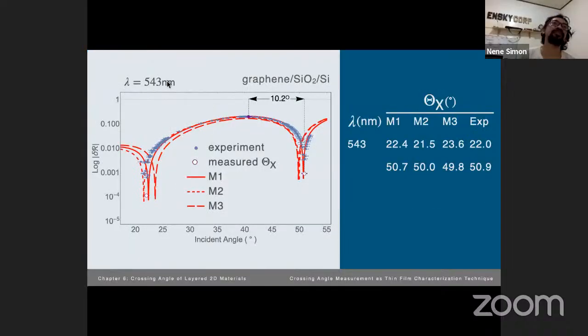So here is the degree of polarization for a 543 nanometer incident light. And as you can see here, model 1 predicts the first crossing angle at 22.4 degrees, the second model at 21.5, the third model at 23.6. The experiment tells us that the crossing angle is at 22.0. The nearest prediction is given by M1. However, M1 and M2 are within the experimental uncertainty. So we measure the second crossing angle in this location. So M1 predicts 50.7, M2 predicts 50.0, and M1 is nearest to the experimentally measured 50.9.